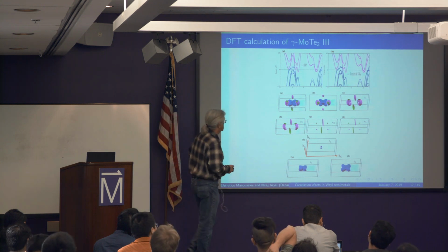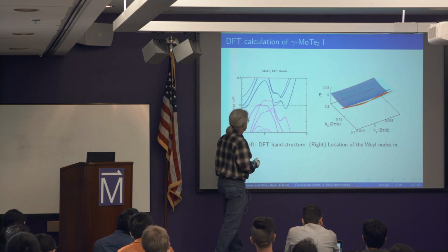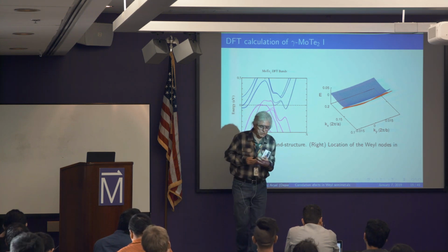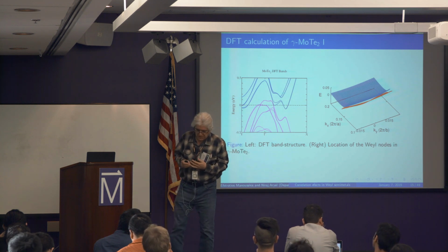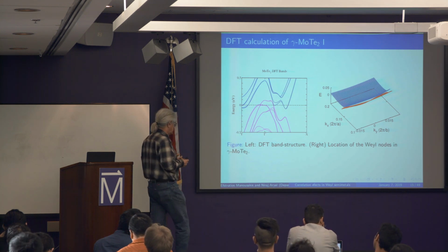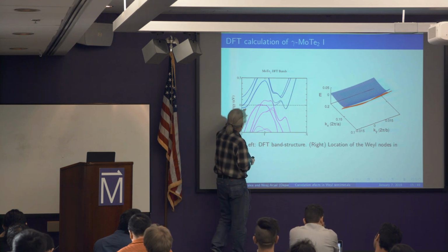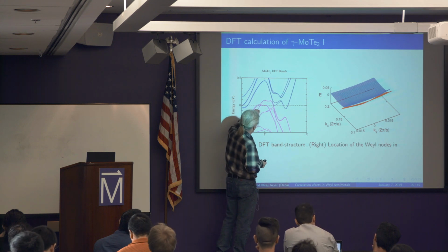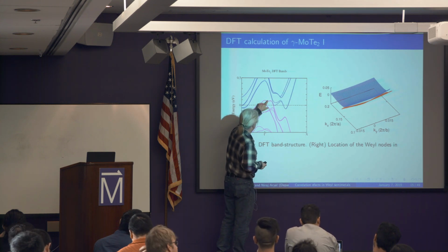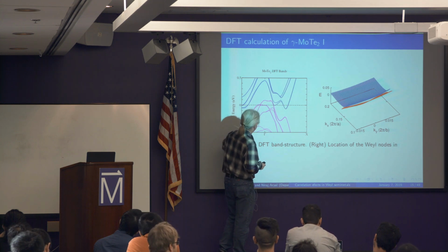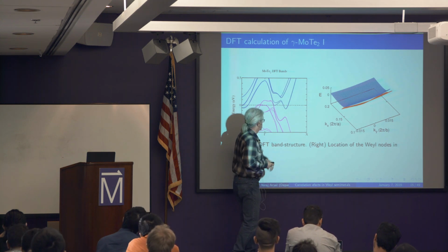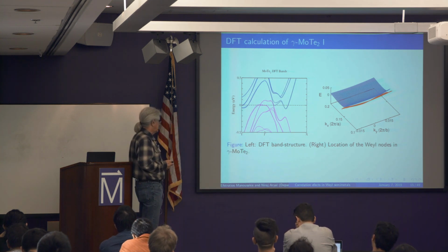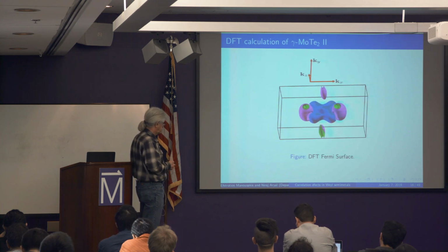The Fermi surface, as you can see from here, has all kinds of stuff because it's orthorhombic, so you don't have the Kramers doublet any more. They split, so you end up having all kinds of bands here. And so these are the hole pockets, you have 2 of them here and another 2 on this side, and the electron pockets. They're very close to one another, but in principle, there are lots of them.